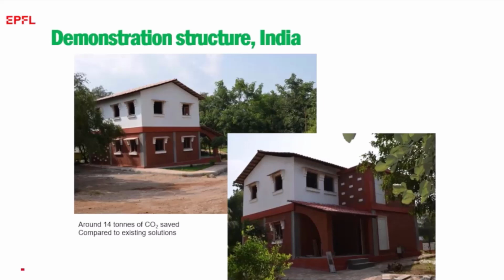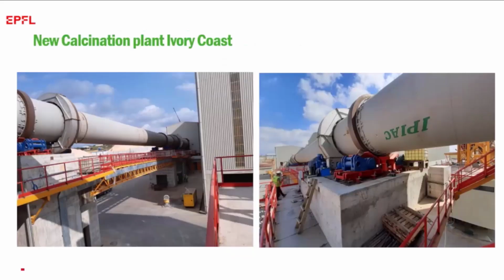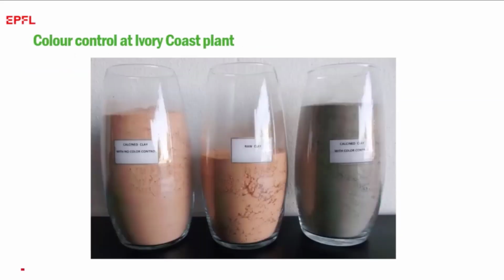And we've taken this through to full-scale building structures. This is a plant which was recently commissioned in the Ivory Coast, and what was particularly interesting in this plant was that we could show that you can change the color of the clay. Many people said, well, people don't want to buy red cement. You can say, why not? It might even be a good marketing strategy. But if you don't want red cement, you don't have to have red cement. This doesn't at all affect the reactivity of the clay because it's just to do with the iron oxide impurities in the clay.